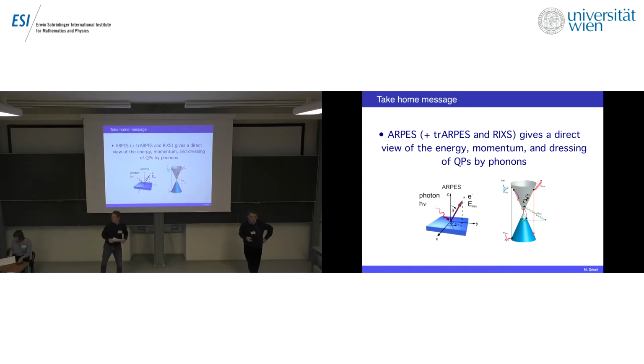There was another question. Yeah, in addition to the photon doping, you could also use doping by exposure to hydrogen atoms. That is a convenient means to put electrons in the conduction band. We haven't done that. Conceivably, yes. The advantage of photon doping is that we can really tune over a broad window the density of carriers. We can use the synchrotron itself to illuminate the material, and then in an oxygen atmosphere, and by playing on these two things, we can really tune the doping over 2 orders of magnitude. We have not done it with hydrogen. Of course, with hydrogen, the point is that you may worry about having surface superstructure, things like that. So it's a different experiment one has to try.